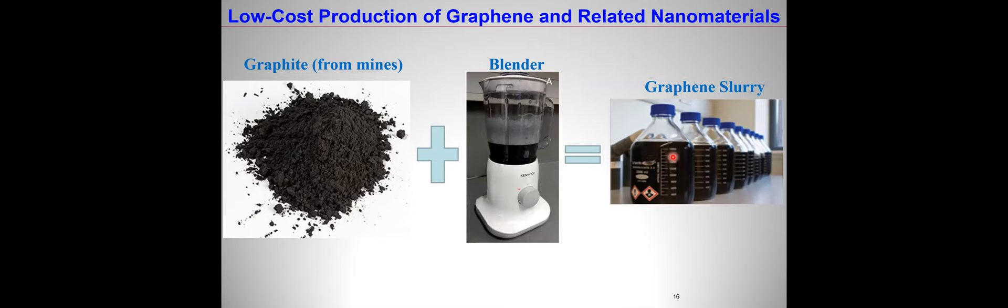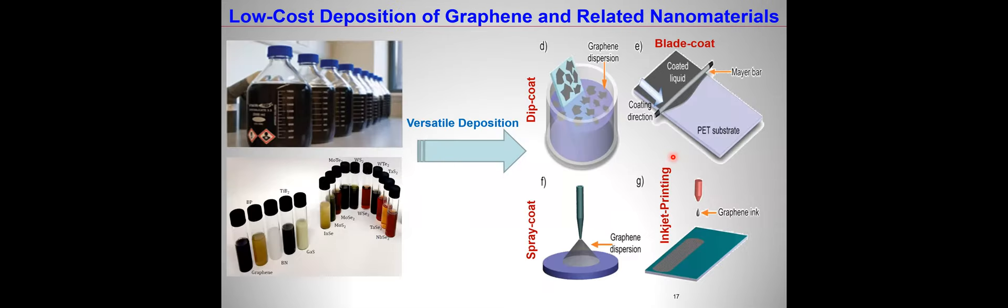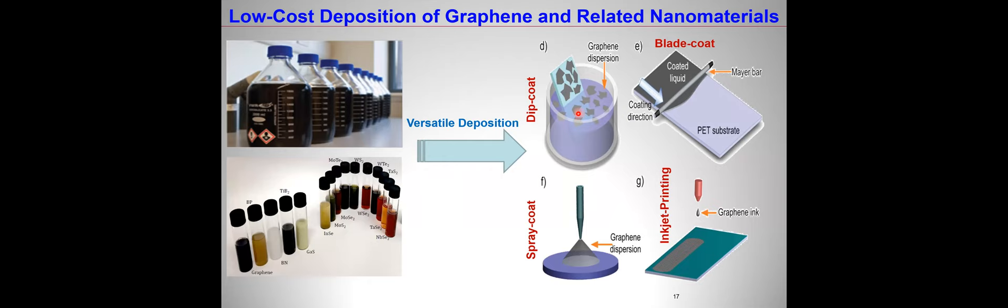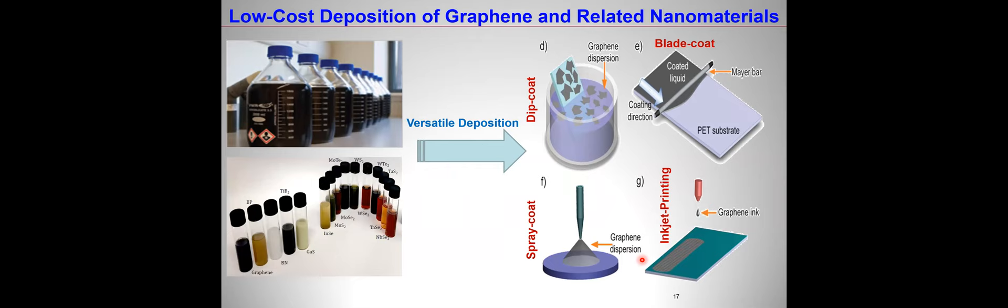There are also other methods of obtaining graphene. One can obtain it from the ground. Several countries have deposits of graphite from their mines. This can be prepared almost as a smoothie in a blender to make a liquid version. This liquid version through sonication will shear this graphite and create graphene. Many companies are selling this liquid phase exfoliated graphene. With this liquid phase forms, there are many ways to deposit this material: dip coating, blade coating for more uniform coverage, inkjet printing for lower cost manufacturing, and spray coating. Very widely useful methods.